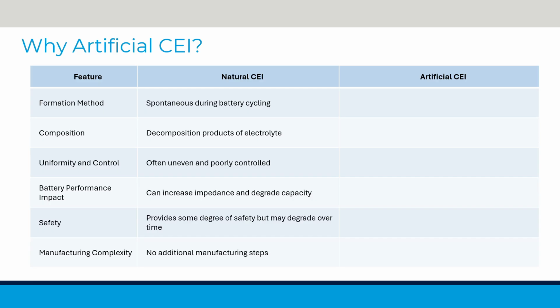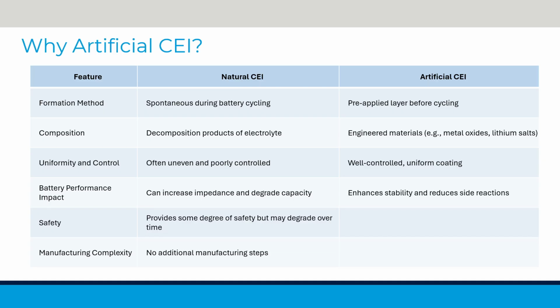To solve these issues, the artificial CEI is deliberately engineered, typically applied to the cathode surface prior to the battery assembly. Various methods are used, including chemical vapor deposition, atomic layer deposition, solution-based coatings, or dip coating methods. The coating is to ensure uniform and controlled coverage on the cathode surface. It helps minimize side reactions between the cathode and the electrolyte, maintain battery capacity, and improve the overall safety of